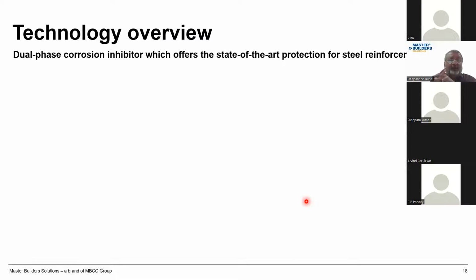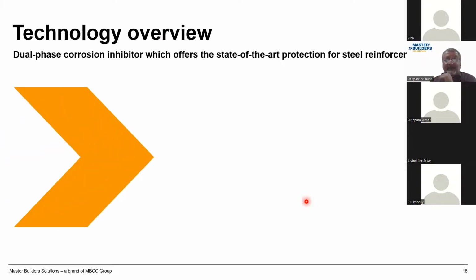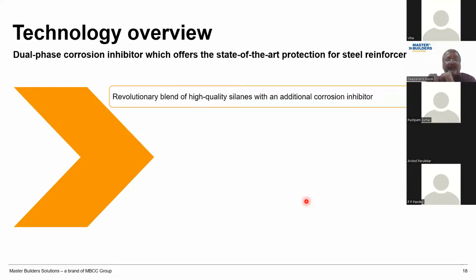So if you look at the technological overview, I'm talking of a dual phase corrosion inhibitor, which offers state-of-the-art protection for your reinforcement bars. Now, what is the highlight over here is I'm talking of a dual phase corrosion inhibitor. What does that mean? It means that it's a revolutionary blend of high quality silane and an additional corrosion inhibitor. Now, what do silanes do? Silanes are very good water repellents. So when you apply the silane on top of your concrete, they are going to remain on the surface, and these molecules with high vapor pressure with corrosion inhibitors are going to penetrate inside.